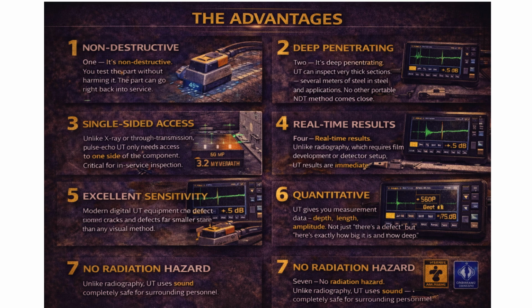3. Single-sided access. Unlike X-ray or through transmission, pulse echo UT only needs access to one side of the component. Critical for in-service inspection. 4. Real-time results. Unlike radiography, which requires film development or detector setup, UT results are immediate. The A-scan shows you results in real time. 5. Excellent sensitivity. Modern digital UT equipment can detect cracks and defects far smaller than any visual method. 6. Quantitative. UT gives you measurement data, depth, length, amplitude. Not just, there's a defect, but here's exactly how big it is and how deep. 7. No radiation hazard. Unlike radiography, UT uses sound, completely safe for surrounding personnel.